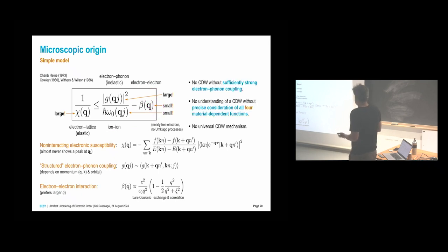And so then you can immediately already give three statements about charge density waves. You will never have a charge density wave without sufficiently strong electron-phonon coupling, because if this is zero, then this is negative, and then you can never be larger than this. So you always need electron-phonon coupling. And there is no universal mechanism. You have these four factors, and they come together in different forms in different materials. And you need to consider them precisely for every material you investigate.